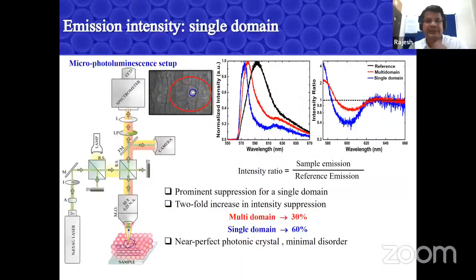And then we developed a setup to collect this emission. Basically, we are collecting the photoluminescence of light. So we have a sample, and we take a laser, which is 532 nanometer.